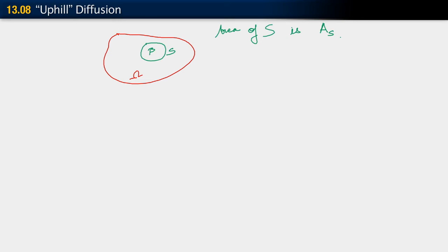Instead of representing it that way with a sharply defined surface, this formulation based on concentration gradients takes the body and smears out that area into a sort of band where things change from alpha to beta gradually.